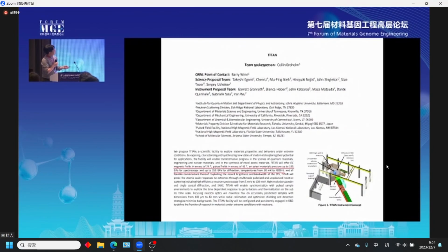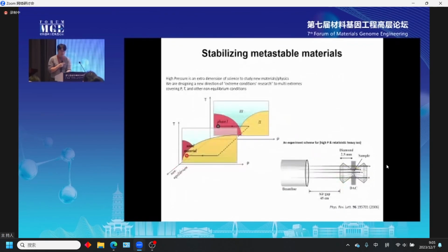This is one of the proposals in the United States. They proposed it some time ago, but it was not successful yet. At Oak Ridge National Lab, for example, they want to establish a very high magnet, like 25 Tesla, and a pulsed field up to 40 Tesla, with around 100 GPa pressure and so on, also very low and very high temperature. If you can combine all these extreme conditions, what can happen? For material science, that should be a very important and interesting research subject from now on. I'm working in that direction, and it's also very good for research where we can apply machine learning.